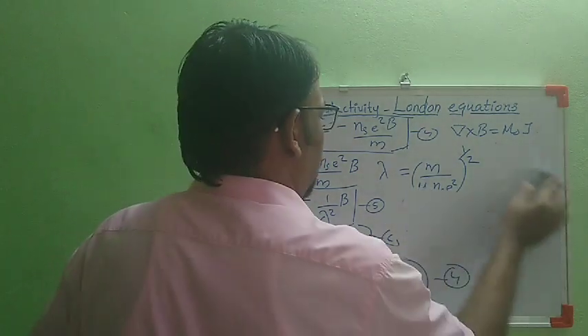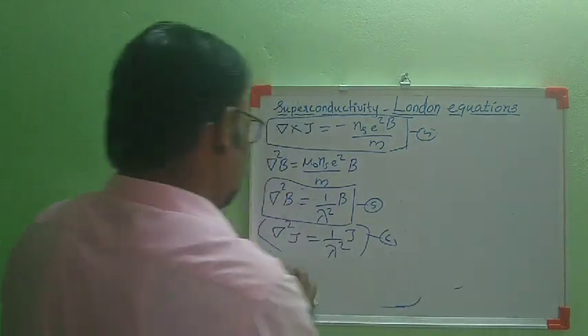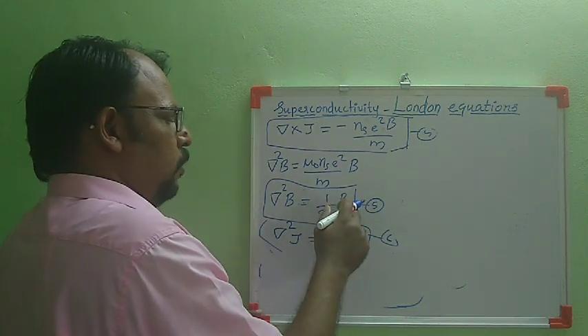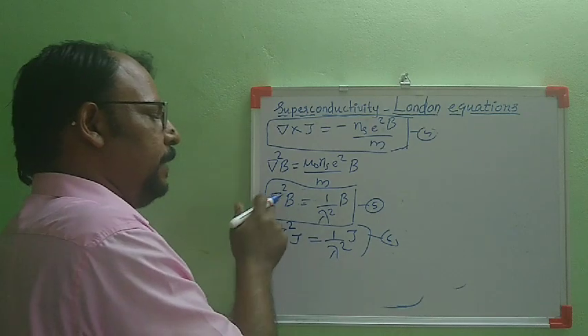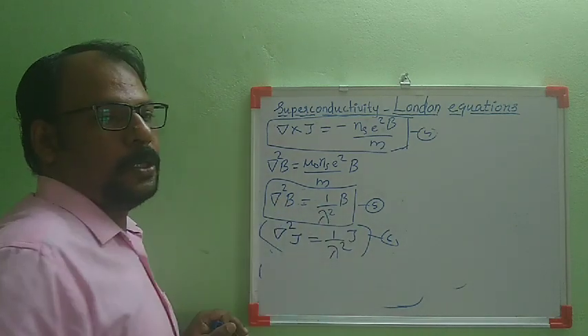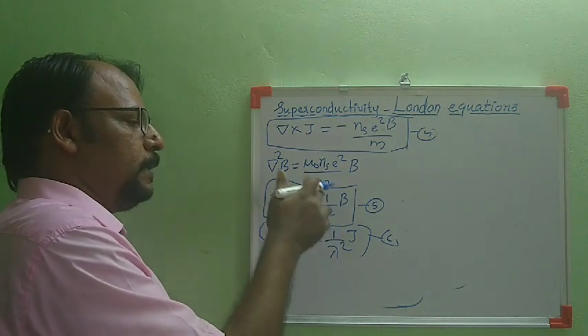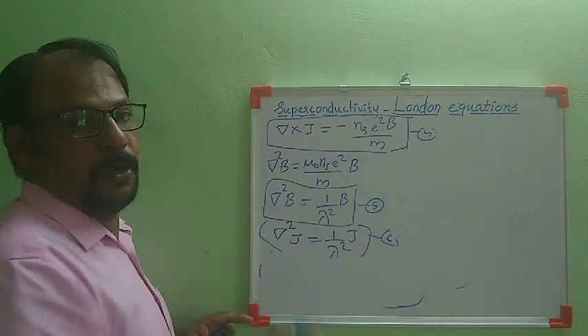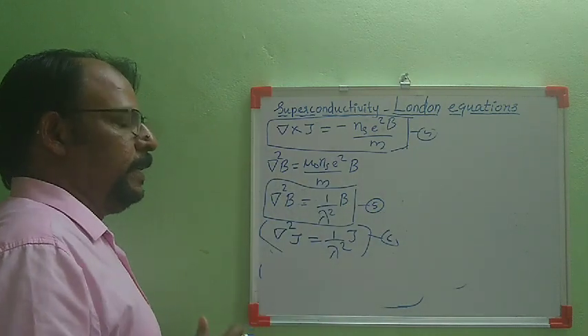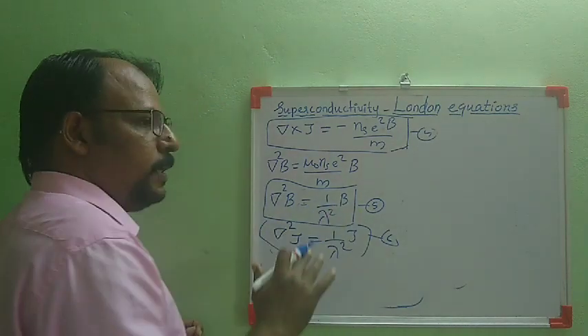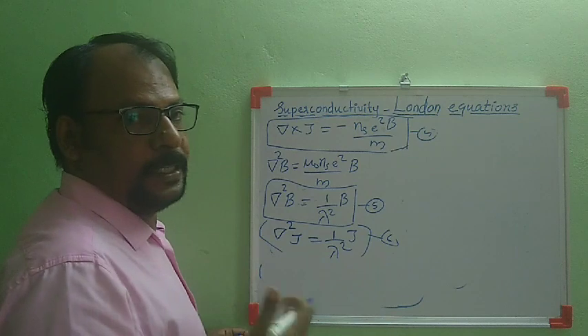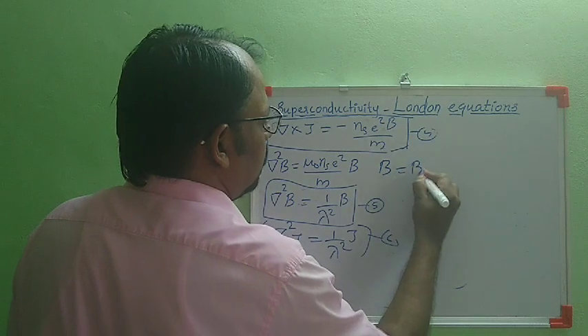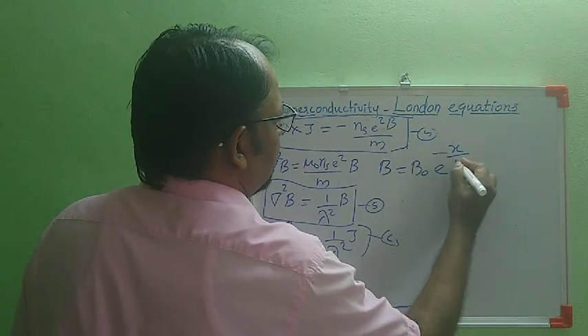When we analyze this equation, if B equals a constant, then del²B = 0, which means B = 0. So the only constant value for the magnetic field allowed by this equation is B = 0. This means inside a superconductor, according to this equation, B is constant only when it is equal to zero.